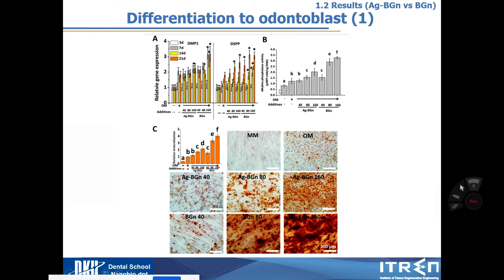And then this ALP, also a marker of phosphate formation, is also highly increased in BGN, but AGBGN is a little bit compromised. But we can say that even though AGBGN is a little bit compromised compared to BGN, compared to the media-only group without nanoparticle, AGBGN has some good effect compared to normal odontoblast medium condition. And when you look at the calcium deposition, BGN has more calcium deposition than AGBGN, but still AGBGN has more calcium deposition compared to odontoblast differentiation media.